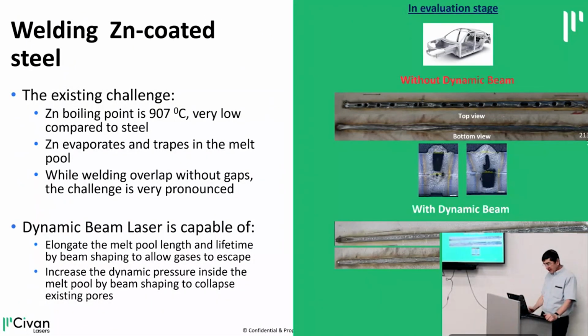And this is the last example. When you have sheet metal, it always comes coated to protect it from corrosion, so it's zinc coated or aluminum coated. In this particular case, this is a customer that has zinc coated material. And when you try to overlap weld coated material, the zinc in the interface evaporates and creates voids, porosity, which afterwards turn into cracks.